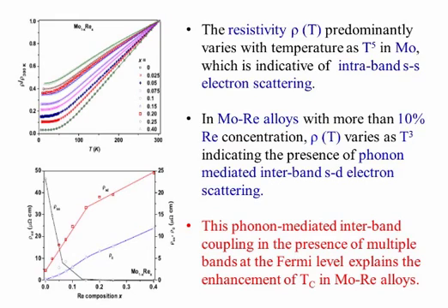The analysis of all these results suggests that such phonon-assisted interband s-d electron scattering in the presence of multiple bands at the Fermi level can possibly explain the enhancement of TC in molybdenum-rhenium alloys above 10% rhenium concentration.